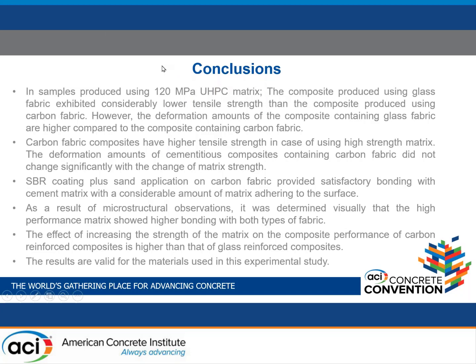When we get to the conclusions, we can conclude this experimental study as follows. In samples produced using 120 megapascal UHPC matrix, the composite produced using glass fabric exhibited considerably lower tensile strength than the composite produced using carbon fabric. However, the deformation amounts of the composite containing glass fabric are higher compared to the composite containing carbon fabric.